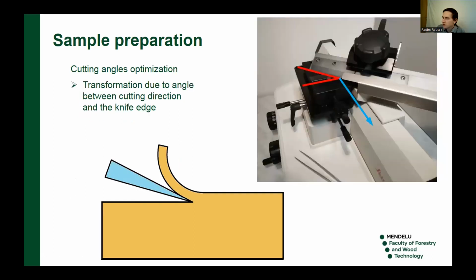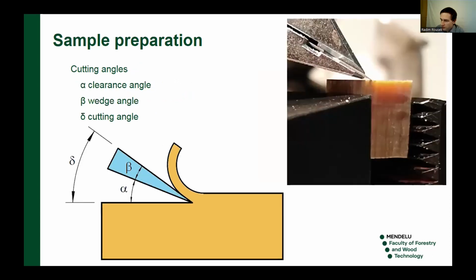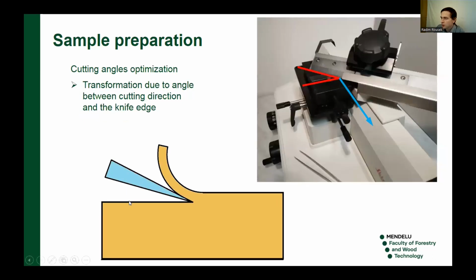There are some other options. We can use transformation of the angles. If we set this angle of the holder this way, as I showed you with these red lines, this angle can help to transform the cutting angles, and the result is the angles are smaller. I can switch again. Look at the drawing now. You can see the real angles when it's perpendicular. If we set some angle, let's say 45 degrees, the transformation makes them smaller. There's not a big difference, but there is a difference. So this decreasing of these angles can help to make smoother surface.